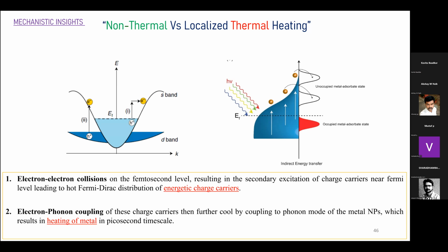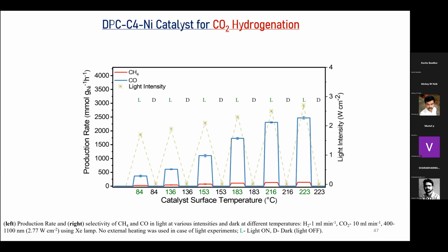We carried out a range of different experiments. This one experiment itself proves it: in the dark there is no activity, but at the same temperature, in the light, there is activity. Clearly it has to be light-assisted and not thermal.